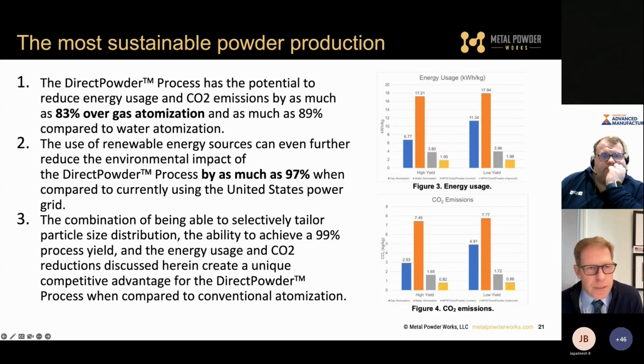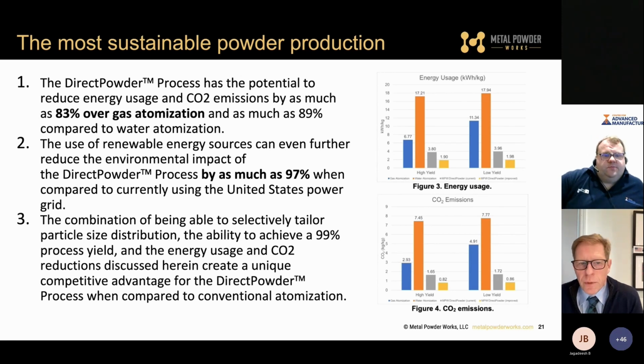We've also done a life cycle assessment, and what we found was that our process emits almost 80 to 90% less CO2 than gas or water atomization. We think that this is really interesting and very meaningful. We don't use a lot of energy in our process, and of course we hardly emit any CO2. And when we switch over to the use of renewable energy sources, because primarily the only source of CO2 emissions is the electricity we consume, we can improve that by as much as 97%.